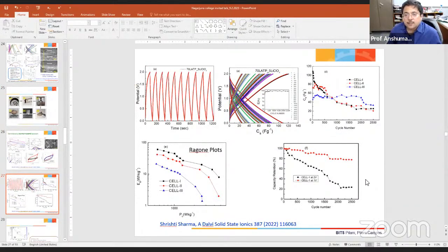Now this kind of potential versus capacitance cycles, if they are very symmetric, then we say high Coulombic efficiency is seen. So high Coulombic efficiency is very much required. That means the charging time and discharging time should always be almost the same. And the final discharge curves also show more than 1000 watt per kilogram of power here, and a reasonable amount of energy in the solid state.